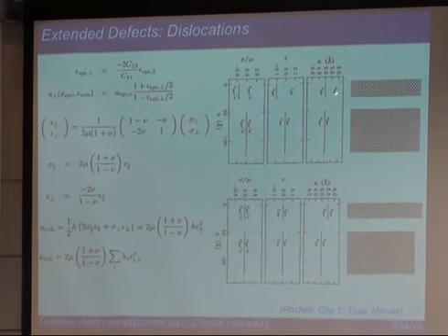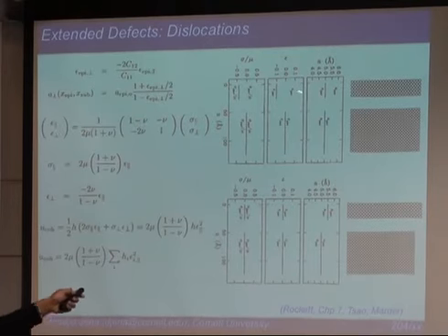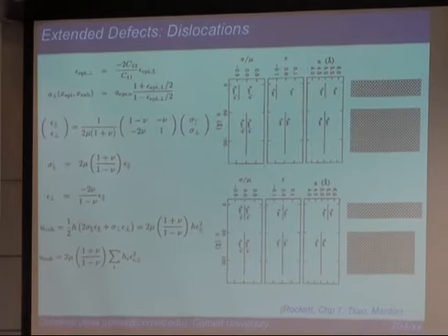And as a result of all this, you now know A perpendicular, A parallel. You can right away write down what is the epsilon perpendicular and epsilon parallel. Right? So that's very clear. The strain in the perpendicular direction is, you see that the lattice constant is larger in the perpendicular direction, therefore the strain is positive. Right? Larger lattice constant minus its own equilibrium lattice constant is positive. Right? Strain in the plane is negative. This is clear. It is a smaller lattice constant in this layer, right? And then that's the distribution now.